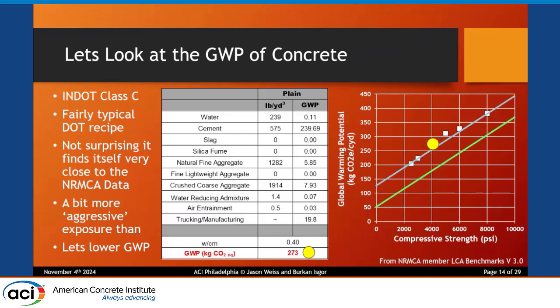and we can put down the global warming potential numbers. If you get up really close to the screen, what you're going to find out is about 90% of this mixture comes from the cement. So the goal is reducing the amount of cement clinker in the mixture, using SCMs, reducing the cement content, doing other things there. Right? It's also not surprising when we plot this particular mixture next to that data, really close to the NRMCA line, because for years there were recipe specifications that the DOTs used, right? And they all used very similar mixtures, right?